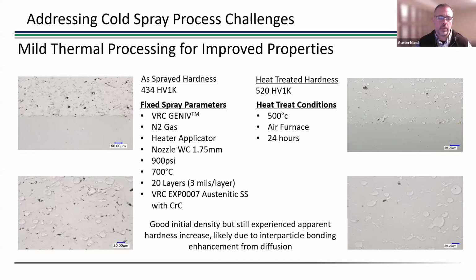This is an austenitic-based stainless steel blend that uses a chrome carbide as a secondary phase. That secondary phase helps you eliminate nozzle fouling. It also helps to consolidate that material really well and give you some wear resistance. The right-hand side of this image is after a very mild heat treatment. It's only 500 C, which for austenitic stainless steel is still pretty low. It was a long time in the furnace though, at 24 hours.